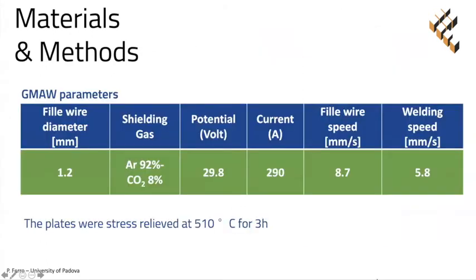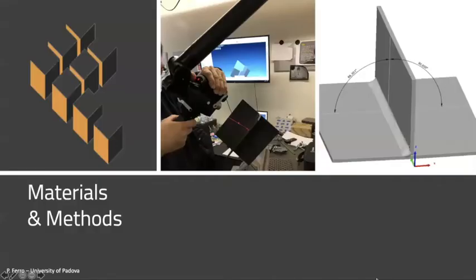More in detail, manual gas metal arc welding was used to produce the samples, and parameters are summarized in this table. After welding, the joints were heat treated at 510 Celsius degrees for 3 hours. The measurement of the joint distortions before and after the stress relief heat treatment was performed using an absolute arm and a support to keep the sample in position during the measurements. The obtained point cloud was then elaborated via software to obtain the angle between the web and the flange.